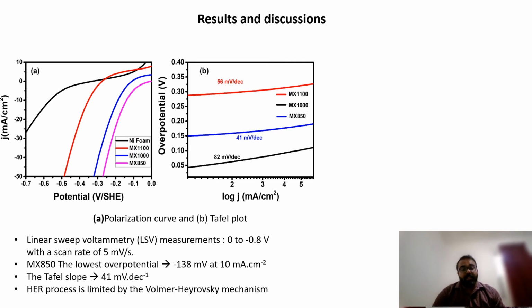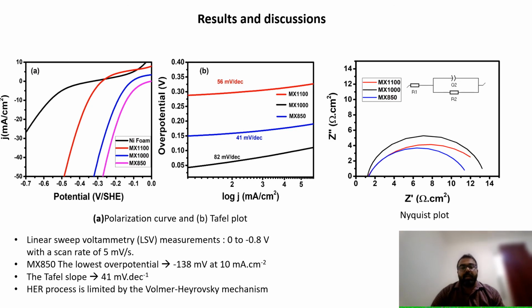And we observed that the sample synthesized at 850 degrees Celsius has exhibited the lowest overpotential, the value minus 138 millivolts at a current density of 10 milliampere per centimeter square, which is the lowest value for a molybdenum carbide MXene as per the report. And the corresponding Tafel slope was 41 millivolt per decade. This process was limited by a process known as the Volmer-Heyrovsky mechanism, or this system obeys the Volmer-Heyrovsky mechanism kinetics.